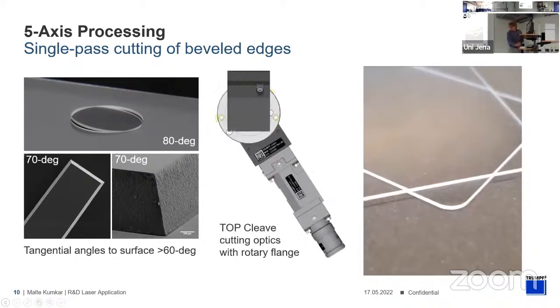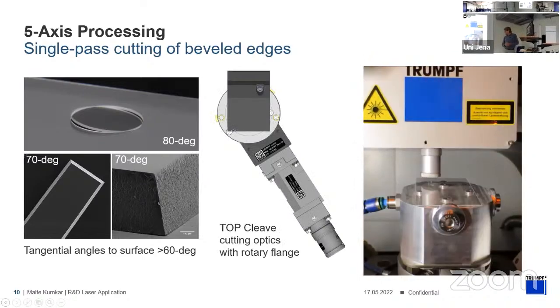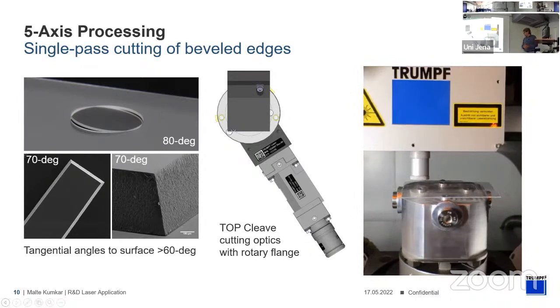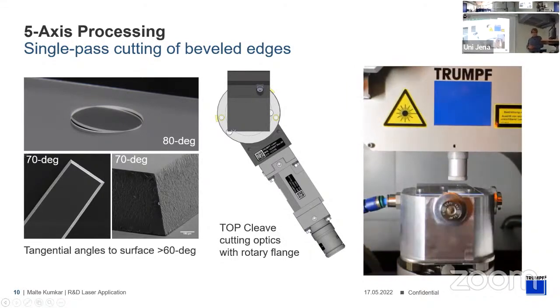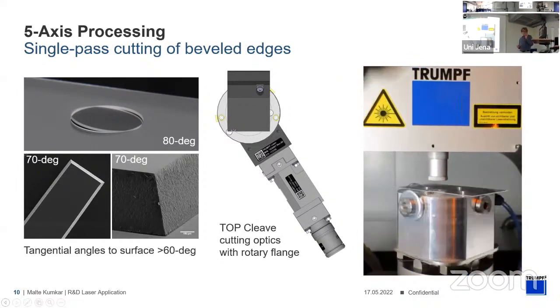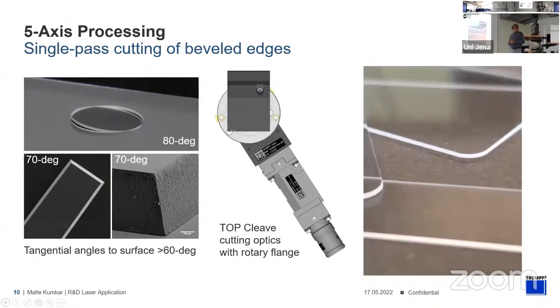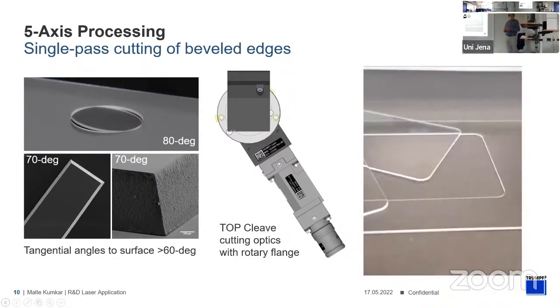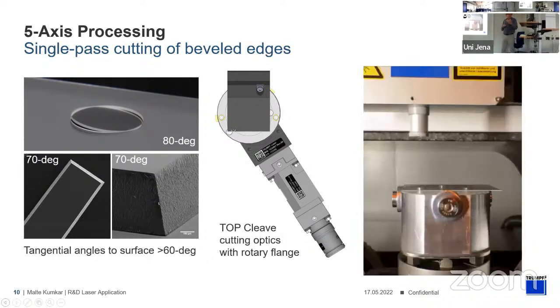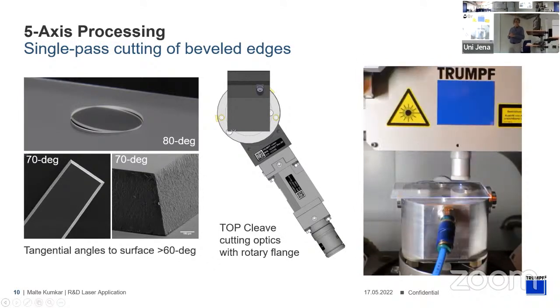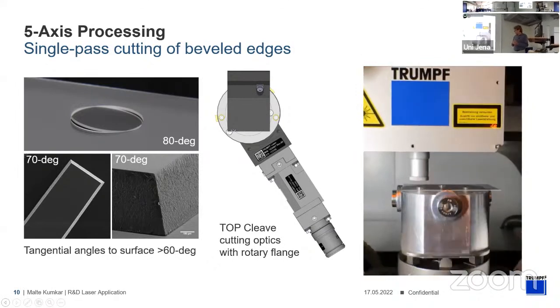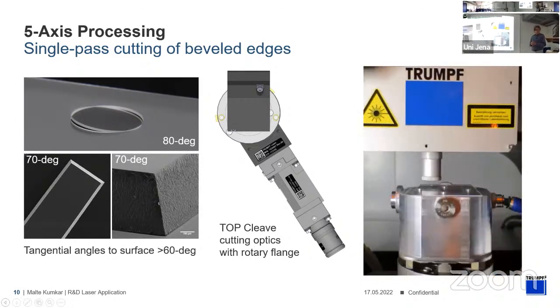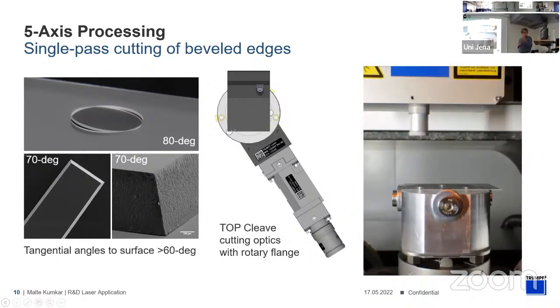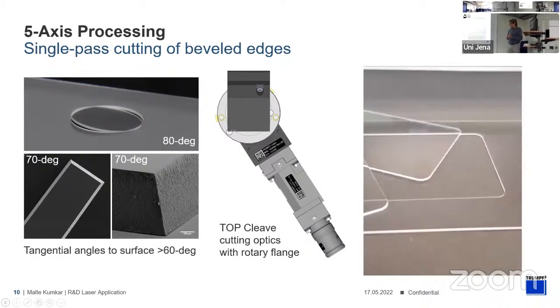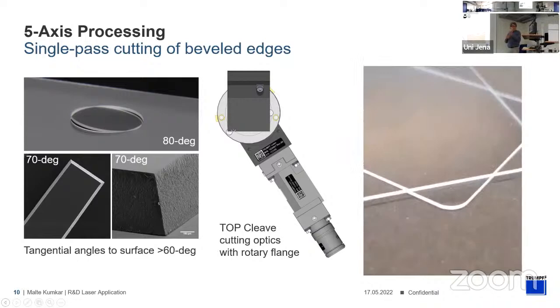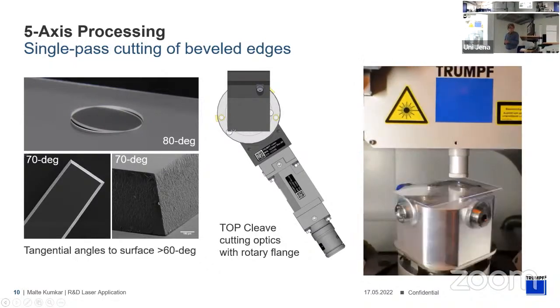So a specialized optics might help, where you can rotate the optics itself. But you enter another problem. The Bessel-like beam, I mentioned it's not critical with respect to aberrations, but in case you tilt the beam, this causes deviation from the conical phase shape. It has to be corrected. Otherwise, the disturbance will modulate in longitudinal direction and will disturb the profile. So the higher the tilt angle, the shorter the length of your profile if you don't compensate the aberrations.